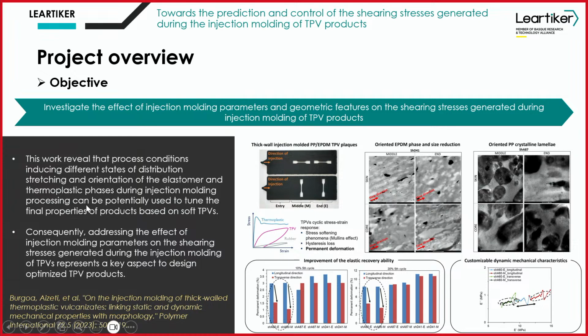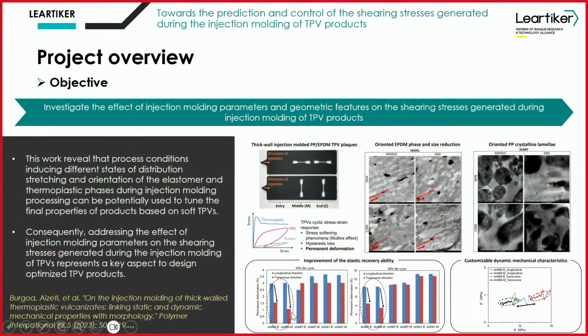And in this work we showed that the process conditions induce different states of distribution in the elastomer and thermoplastic materials that we have in the TPVs, and that these processing parameters can potentially be used to tune the final properties of soft TPV-based products. Because as you can see, for example, here, by considering these process influences, we were able to reduce the permanent deformation, the plasticity that we can have in TPEs.